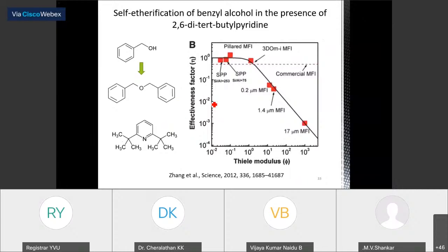So this reaction has been done in the presence of this kind of a base. Okay. So when you use this base, it will cover all the acid sites which are present on the surface. Okay. So it will selectively attach with the sites present on the surface. So the sites present inside the pores will not be affected by this. So you can effectively characterize the acid sites, and the influence of the difference in porosity by way of introducing hierarchical pores can be studied when you perform the reaction after masking all the surface acid sites using this kind of di-tert-butylpyridine.